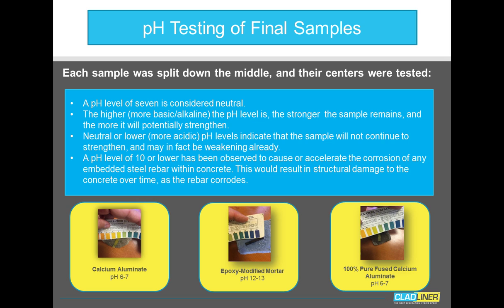If the pH is neutral or lower, we start edging towards more acidic environment. It indicates that the samples will not continue to strengthen, and once it drops below neutral, we actually find that concrete will begin to start weakening, and as a result, start falling apart.